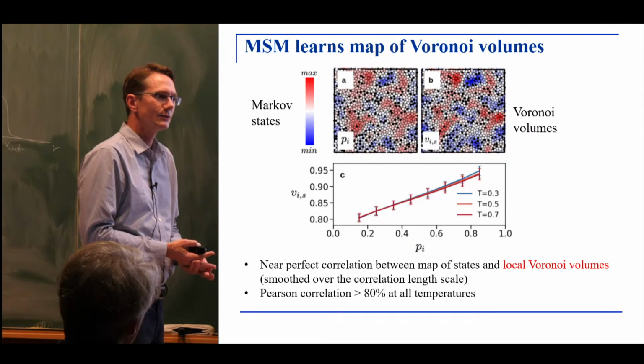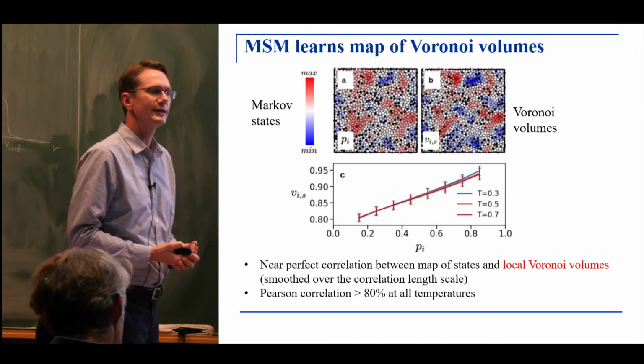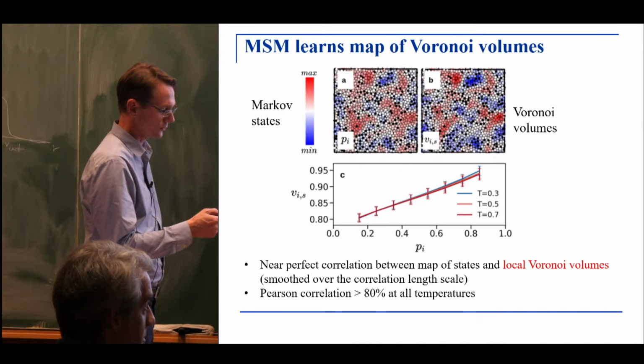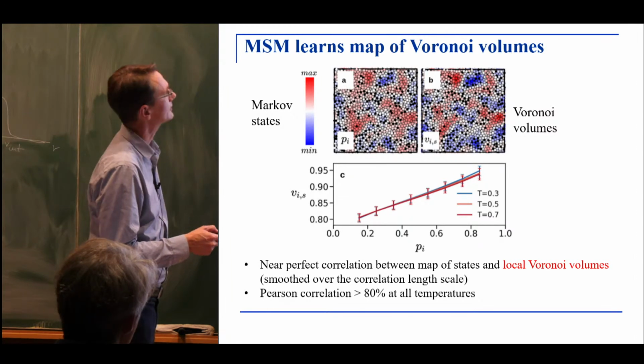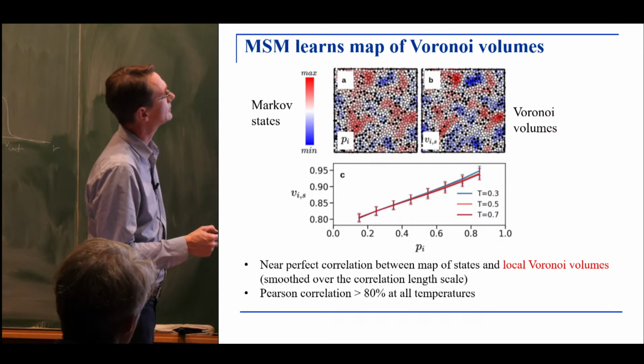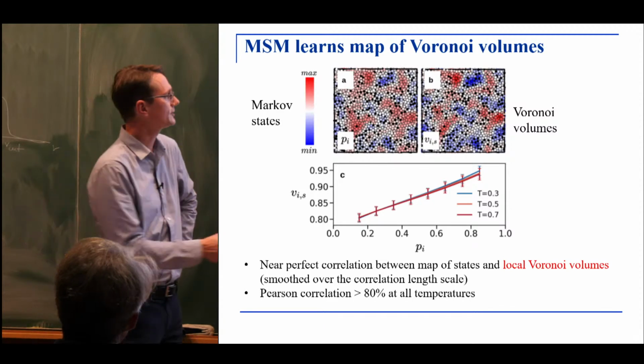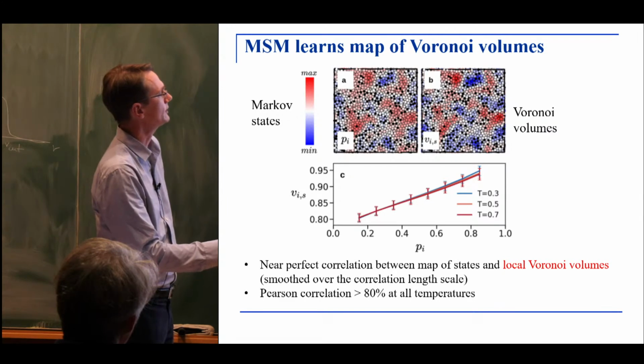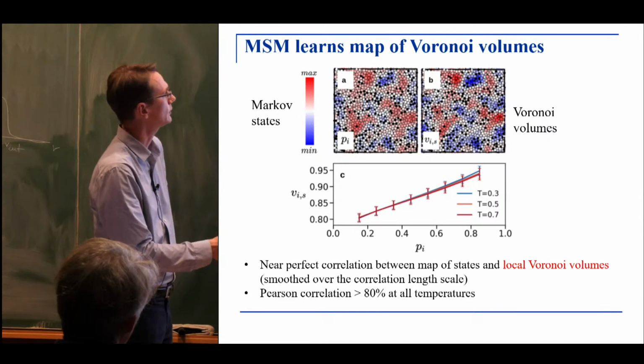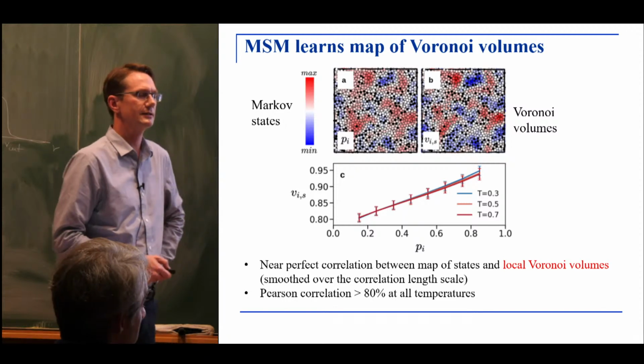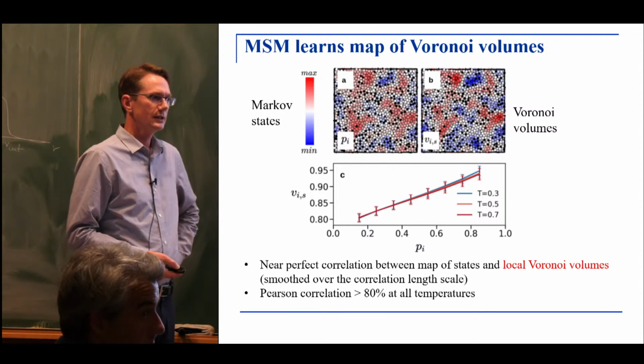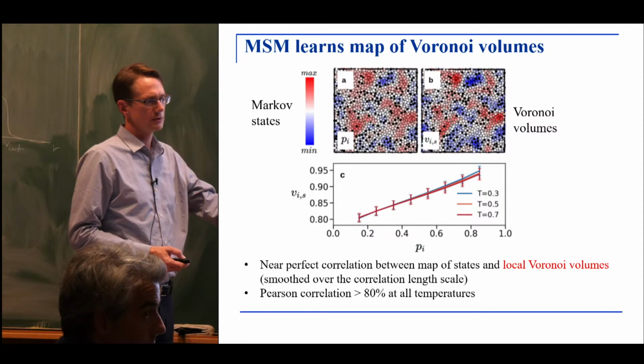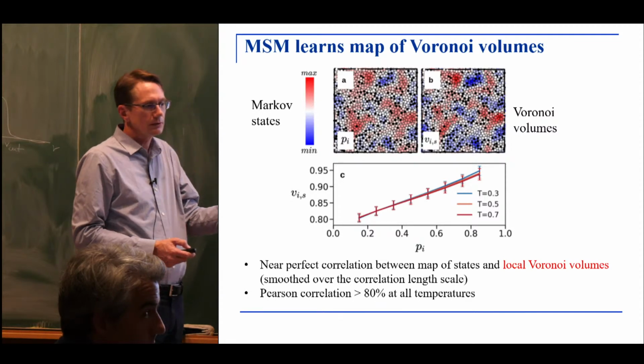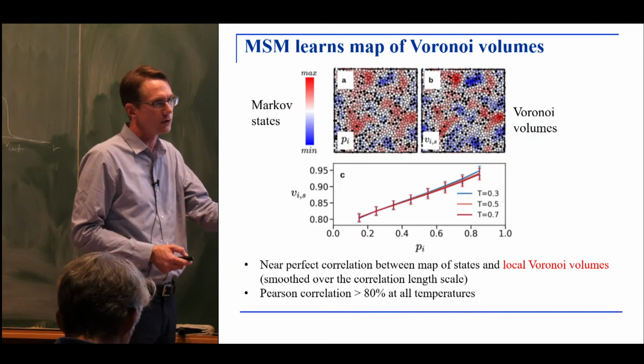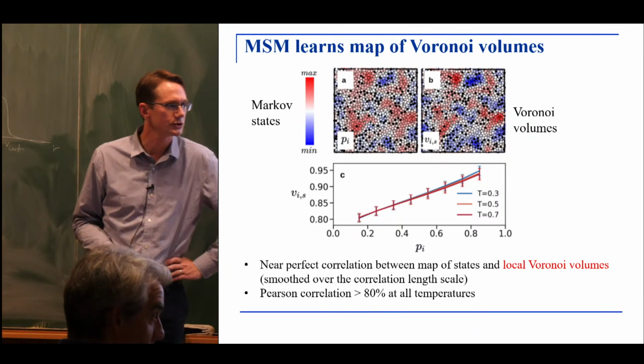I still don't get. Well, that's what they are. The cluster of red is a cluster of small Voronoi volume. The cluster of blue is a cluster of large. So this is what the correlation graph at the bottom shows you: small Voronoi volume, small probability to be in state 0. So the method does pick out as the slowest variable these local volume fluctuations. That emerges from this machine learning approach.